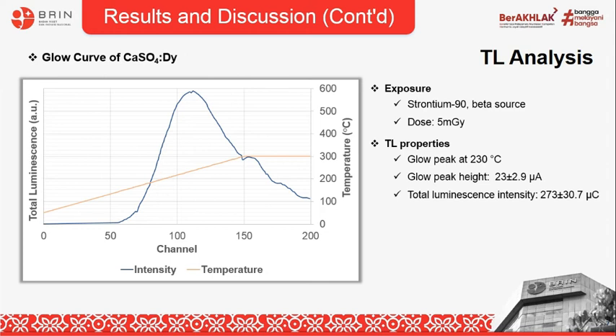After being annealed at 300 Celsius degree, the powder was read once more, and it turned out that the peak had been emptied at the first reading, indicating only a few electrons were left behind.